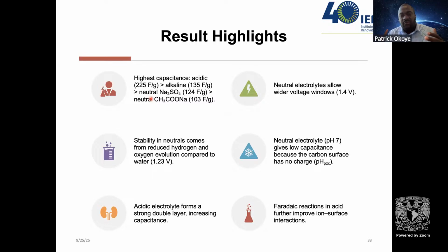Of course, if you use metals and the rest, you may have a far higher capacitance, but then you are synthesizing those materials to be used. Also, we found that we cannot use neutral electrolyte because it gives low capacitance. And since the surface of our material is also electrically neutral, the neutral electrolyte does not work in this. So acidic electrolyte forms a strong double layer and increases the capacitance that we have.